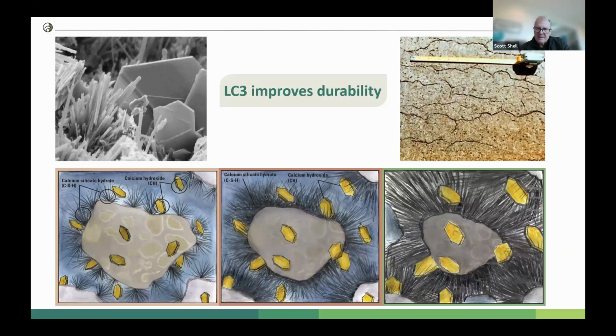Another mechanism is ASR, alkali-silica reactivity, and that's what you're seeing in the upper right-hand corner. In fact, that Ash Grove plant that I showed earlier in Nebraska, they have a serious problem with ASR, and the Department of Transportation is very keen to solve that by using the LC3 cement. So they are supporting the use of these high clinker replacement cements like LC3.